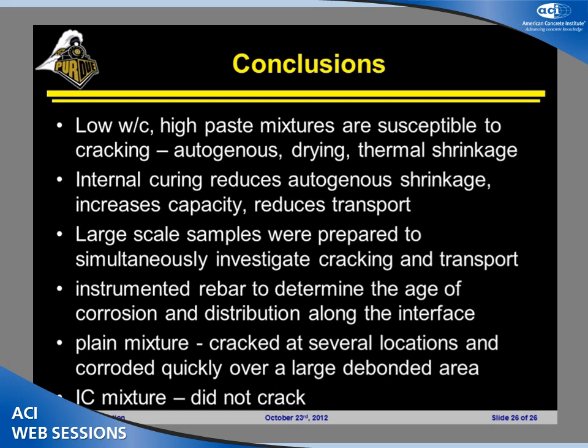So I wouldn't make an argument that a 12% aggregate is a lot better than a 14% aggregate, or I don't think it's there. And I'll let the sales guys who sell 12 and 14% aggregates fight with each other about that. I think all of them work. Where I think really the sweet spot is in this is you can go to these higher performance mixtures because you have the benefit of the internal curing. So now you can conveniently, safely put out something that's like a 0.36 with the silica fume, so you can really reduce your transport properties. You're not as worried about your thermal cracking, your autogenous cracking, because you've essentially taken the autogenous part of this off the table.